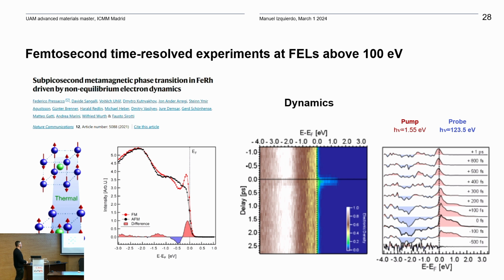So the idea of the colleagues was to study this with a pump-probe experiment to see the dynamics, because there is a lot of research in the literature, and it's not yet fully understood what is the time scale that defines this transition. So they did an experiment pumping at 1.55 electron volts, so 800 nanometers, and they probed with 123 eV. What you can see as a function of time is something like this. This is before time 0, when you are in the antiferromagnetic state, and then after 0 you have a lot of hot carriers at the beginning, and then immediately your system goes into the ferromagnetic phase. There is a lot of debate in the literature because not everybody is convinced that the results are fully conclusive, but at least it's a step forward to understand what's going on.